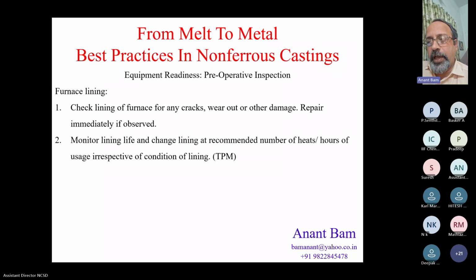Check the lining of furnace for any likely crack or worn out lining or damaged lining if you are using induction furnace. Then repair it immediately if observed. Monitor the lining life and change the lining at recommended number of heats or recommended number of hours of operation, irrespective of condition of lining. This becomes a part of total preventive maintenance, TPM. If you maintain the lining in its good condition, then naturally the downtime of the equipment is zero. Next slide, please.